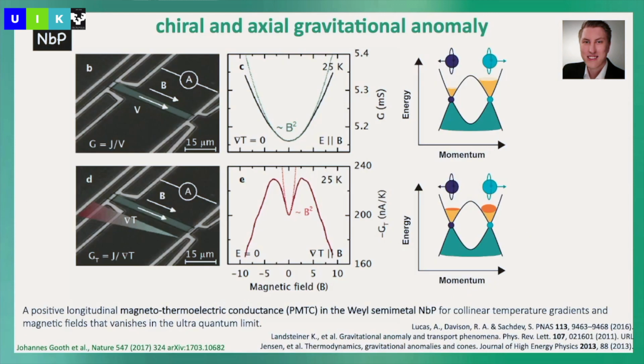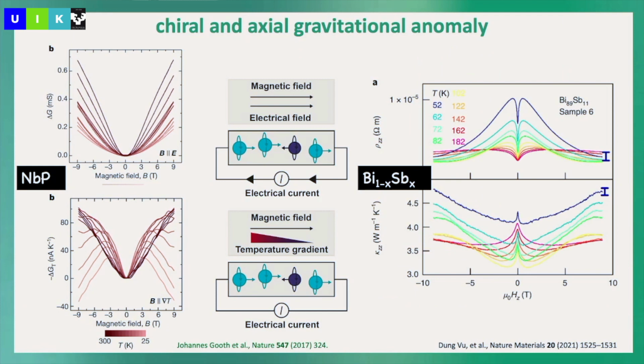I think this is very fascinating, this fundamental broken symmetry, and I think one should think even more about more experiments. Nowadays, this was also done for other materials, like here for this bismuth antimony. You can see very nice effects, even up to quite high temperatures. So also here you see the chiral anomaly with this temperature gradient. This was work from Jos Heremans, and people have now done it in many other materials, and it's very typical for these Weyl semimetals and so on.